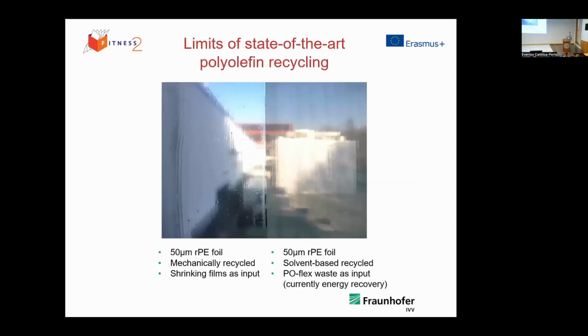On this slide, you can see a comparison of two films which are made of recycled polyethylene. To the left, you can see a mechanically recycled polyethylene film, which was made of shrinking films as an input, so a very, very pure and separately collected waste stream. And you can already see that there are a lot of gels inside of the foil, which also disturb the mechanical properties. And this was just one recycling loop with mechanical recycling.